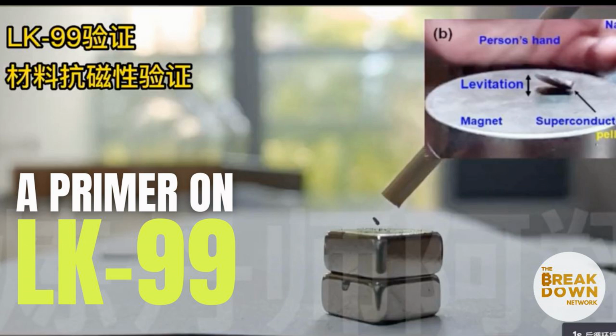LK99, by contrast, starts out superconducting and has to be heated beyond the boiling point of water to reach its critical temperature. The only somewhat strange result here comes at temperatures just below the critical temperature. At room temperature and above, the resistance of LK99 remains at zero, as far as the testing equipment is able to measure. But it starts to rise ever so slightly once temperatures reach 60 degrees Celsius and displays a smooth upward slope until the sample hits 90 degrees Celsius, at which point it stays flat until the critical temperature is reached. The researchers did not attempt to explain this.